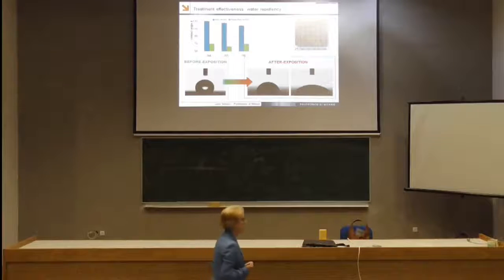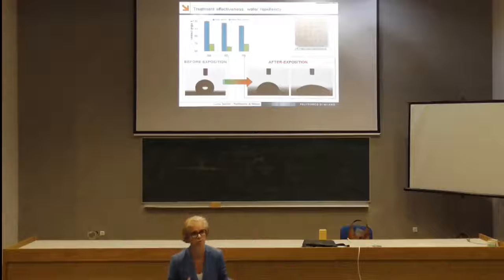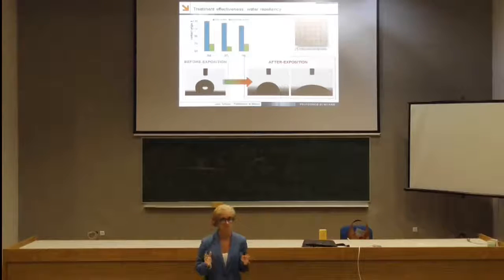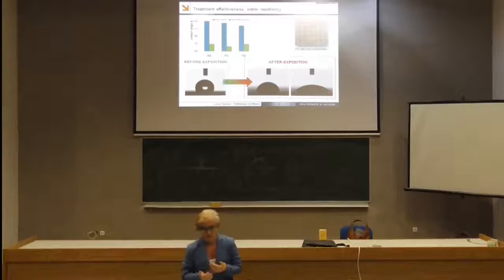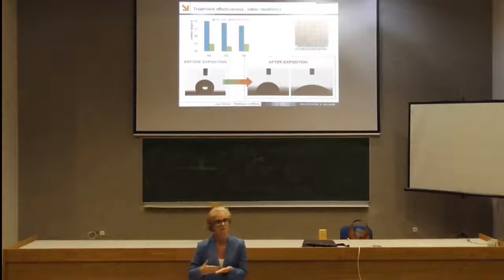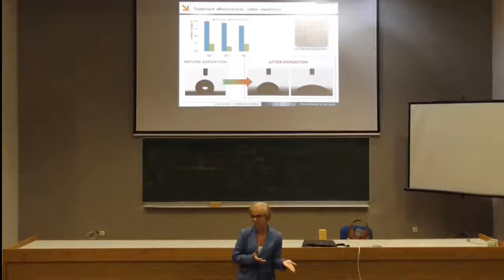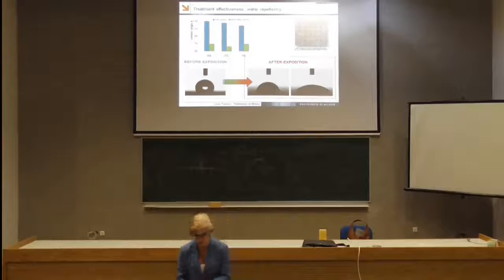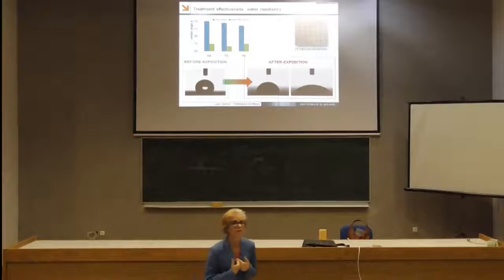The same happens for the ability of a coating to be water repellent. At the beginning, this treatment is highly water repellent, showing a contact angle with water of about 130. It's a very good water repellent, because you know that water repellency is gained over 90. But during time, with this situation of dust and rain, so the exposition to the outdoor condition, after 1 year of exposition, the contact angle is reduced to about 70. So this for us means that the marble is no more protected.